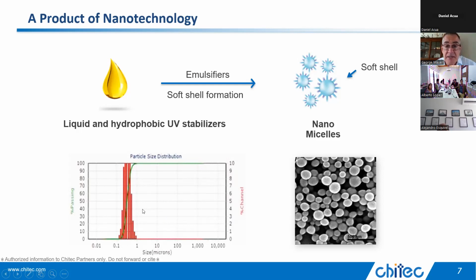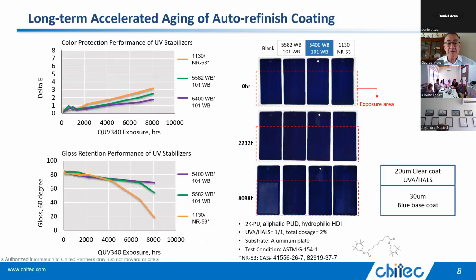Extremely tight particle size distribution. So a really good material. Here's some performance, and I'll start off by saying that this test does not involve exterior testing or exposure. This testing is really just done on a QUV. It's the 340 bulb, which simulates sunlight pretty accurately up through about 350, 360 nanometers. It's very, very good at reproducing sunlight. Isn't quite as good out towards 400, but it's a good test.